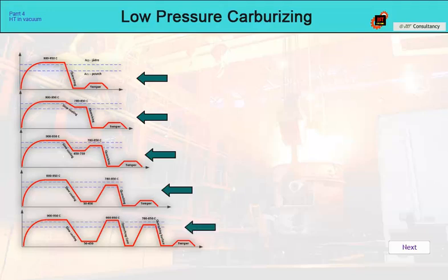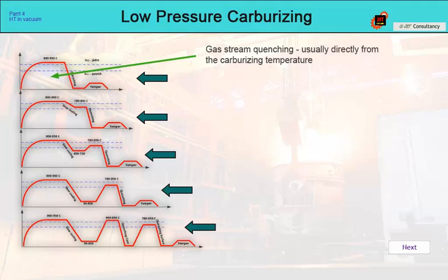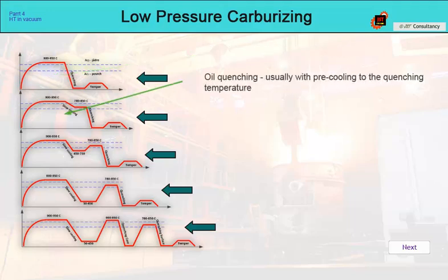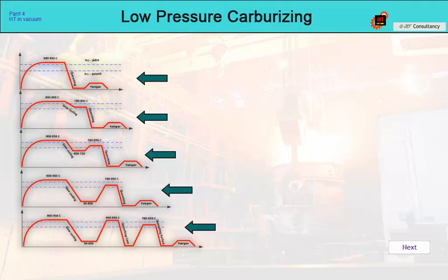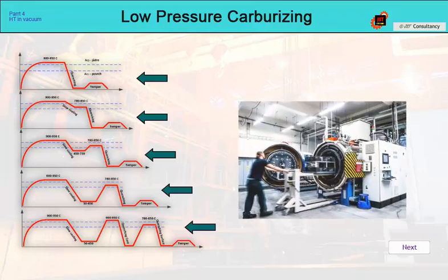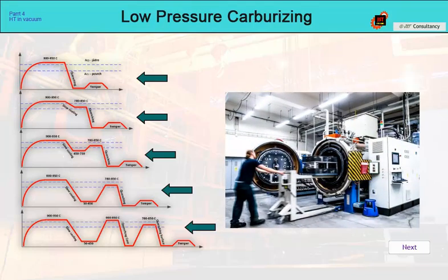There are many ways. However, in low-pressure carburizing, the opinion has become established that if we harden in a gas stream, in nitrogen or helium, we harden directly from the carburizing temperature. If we quench into oil, we must pre-cool the load from the carburizing temperature to the optimum quenching temperature. If we have a single-chamber vacuum furnace with 15 bars of nitrogen, and LPC is only there as an extension of our technological capabilities, we have no choice. Unless there are any major reasons against it, we will quench directly from the carburizing temperature.